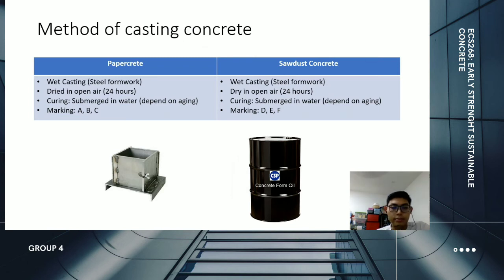Alright, so this is the method of casting concrete. For the papercrete, firstly we use the wet casting method, which means when the mixed concrete is fresh and wet, we pour it into steel formwork, so the workability is good. The wet concrete mix fills the spaces inside the steel formwork, and we also use concrete form oil before we pour the mixed concrete, so the concrete is easier to release from the steel formwork.